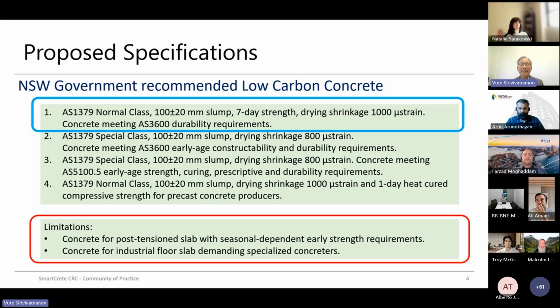In identifying this concrete, they must also meet the 1379 7-day strength requirement, and also meet all the requirements in the Australian Standard 3600 for 50-year design life. The second group, which I just mentioned, is again 1379, but in this case special class concrete with special requirements. In particular, the requirement for early age constructability and durability requirement in 3600.